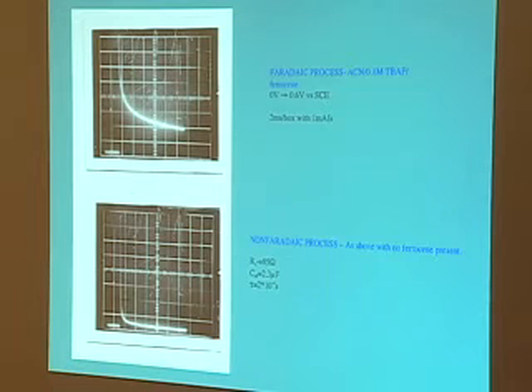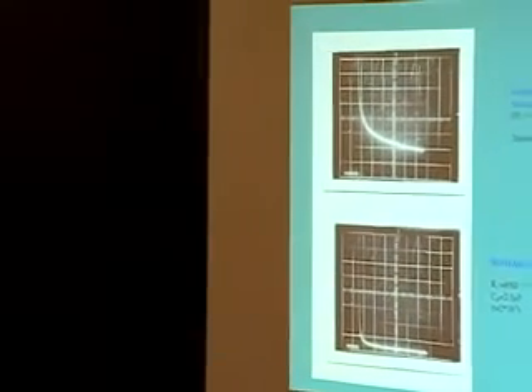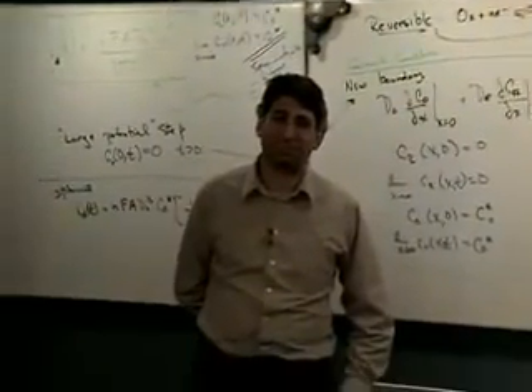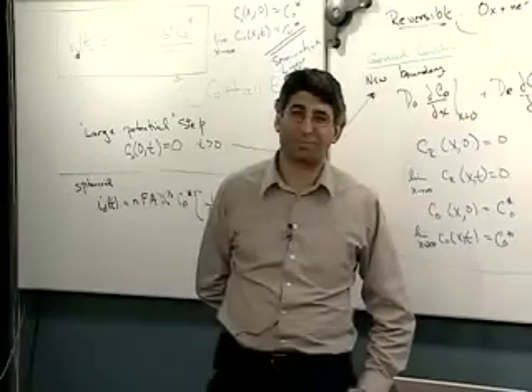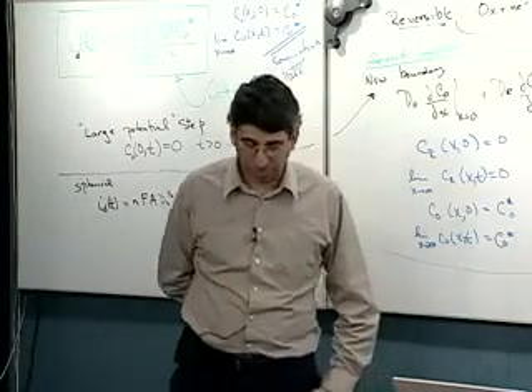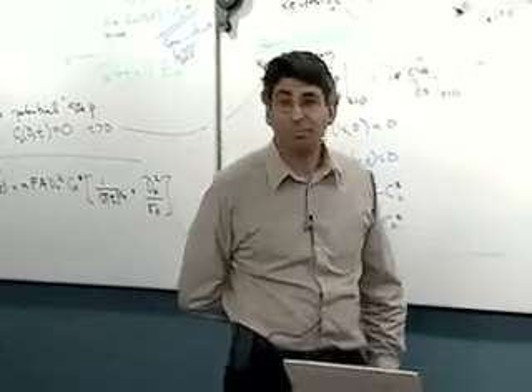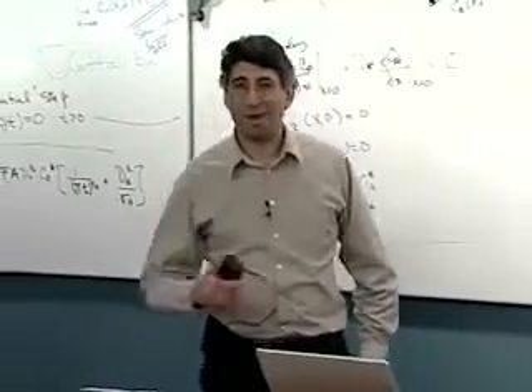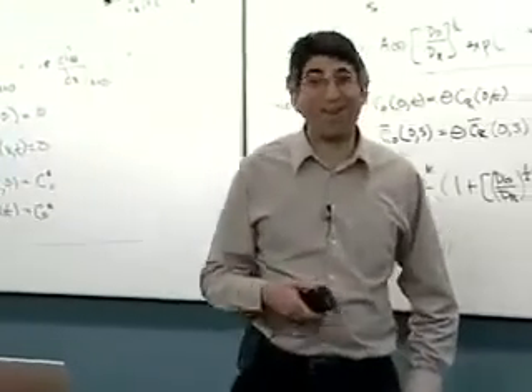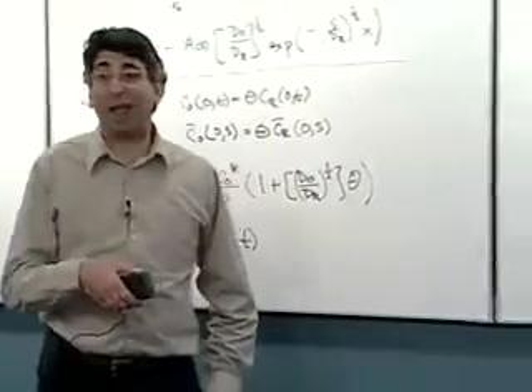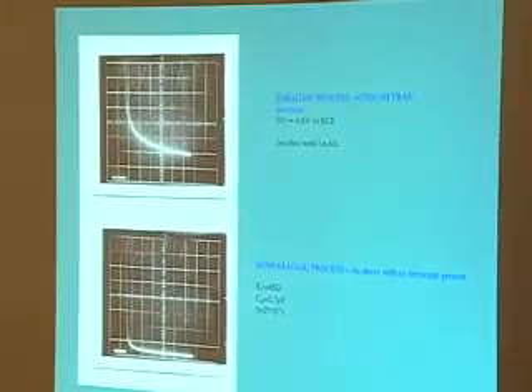In this semi-infinite approximation, you're basically assuming nothing comes in sort of from the side. No edge effects, correct. Whereas in the spherical one, you basically have that. So I would guess in the semi-infinite, you should get a constant current term for stuff that's coming in from the side, too. And so that would also affect you. Absolutely. And that's why I'm saying my electrode, although planar, is not infinitely planar, right? So there is an edge here. And of course, the question is, what's the ratio of edge to area? And one can try and make that large, but you run into a problem when you do that.